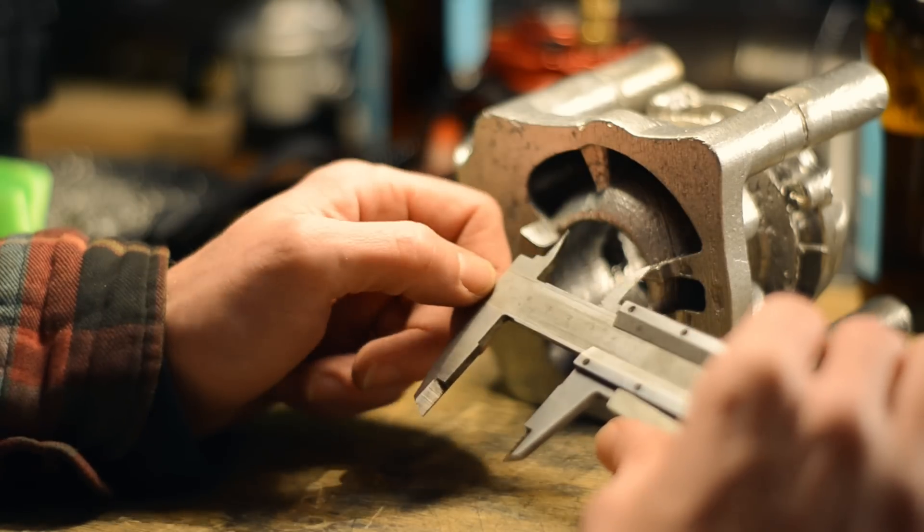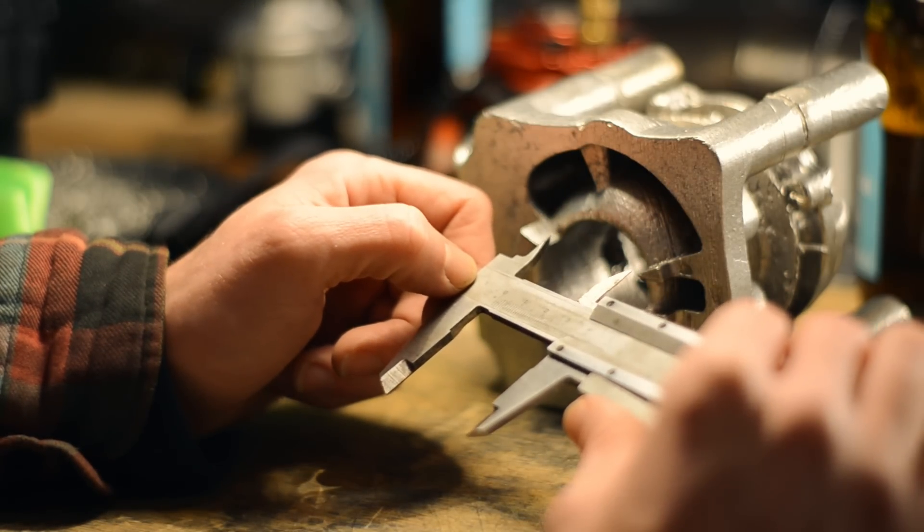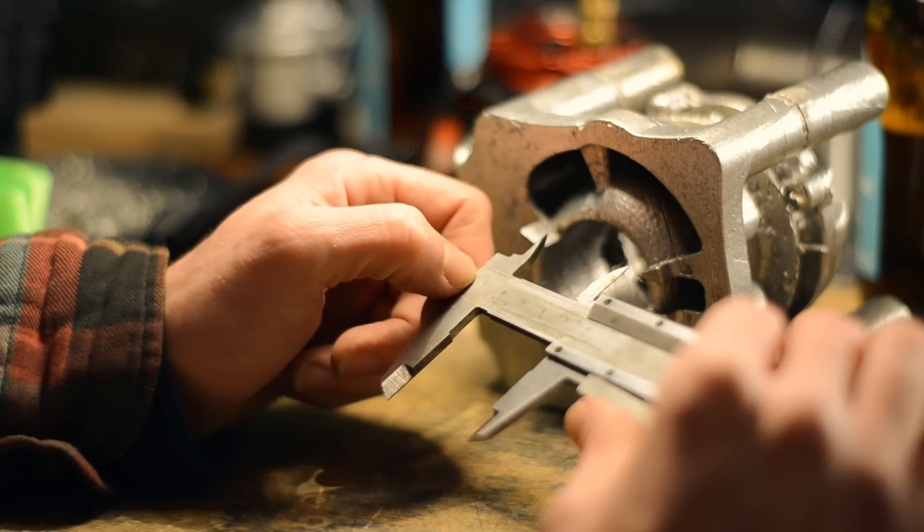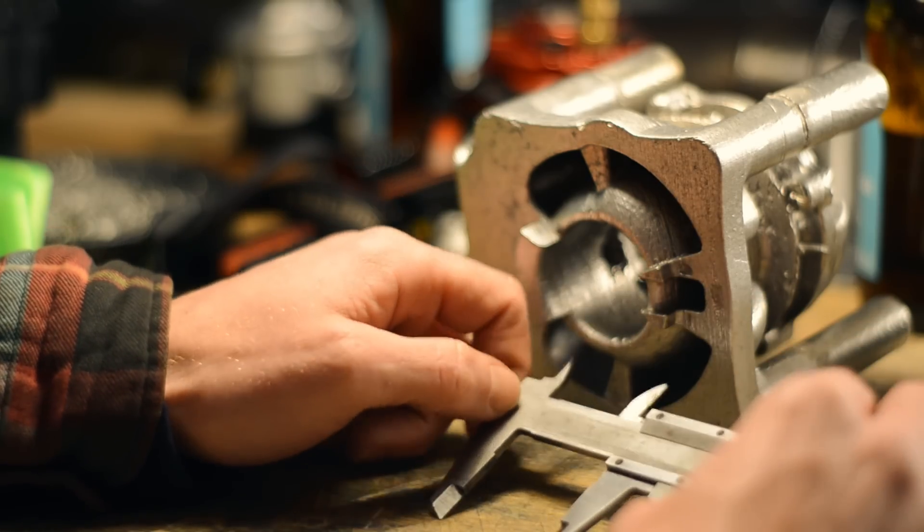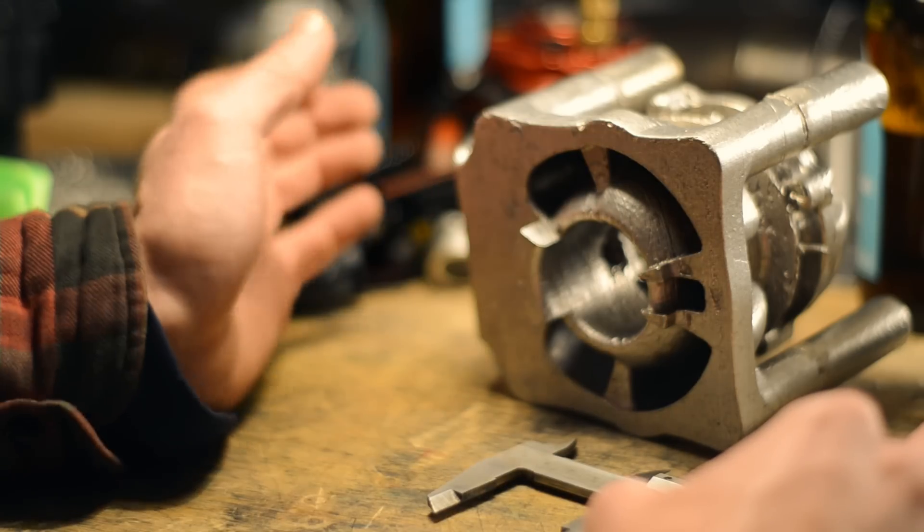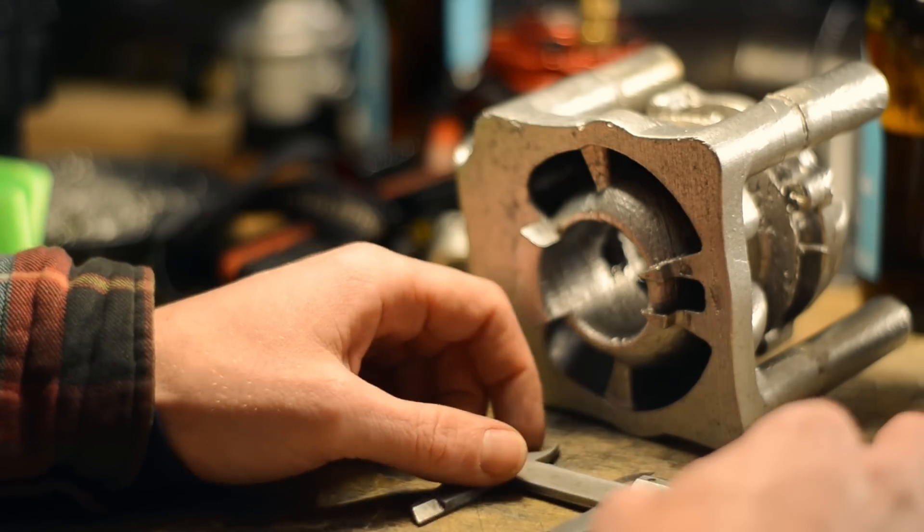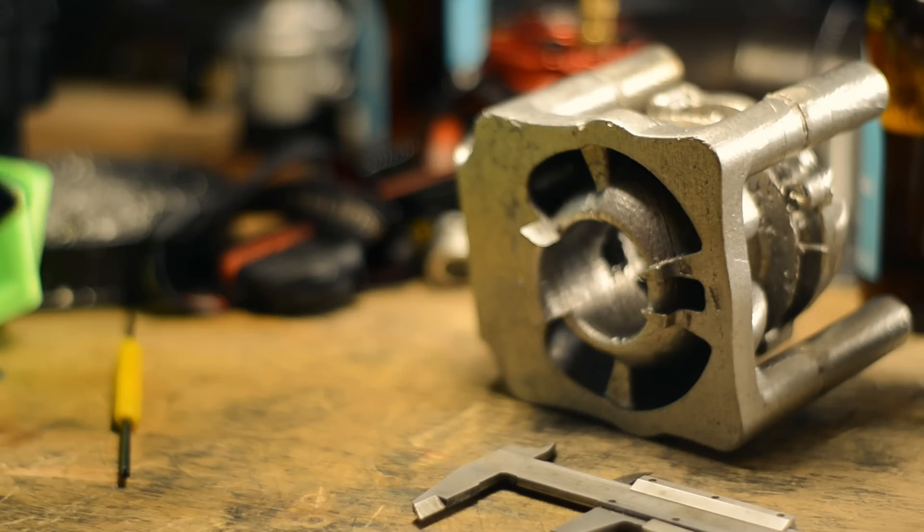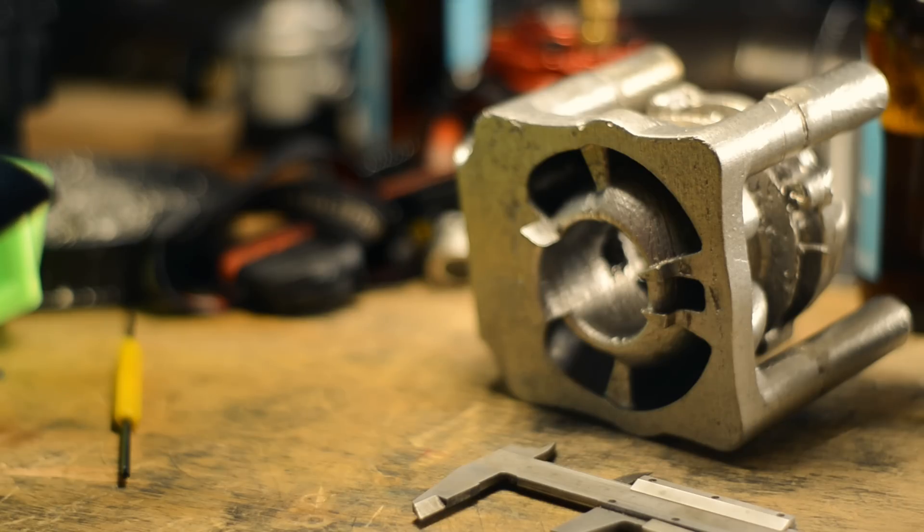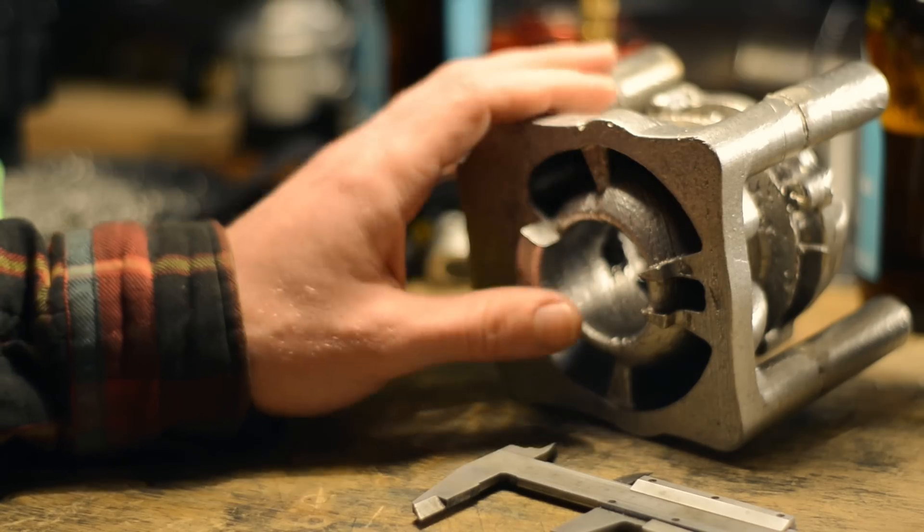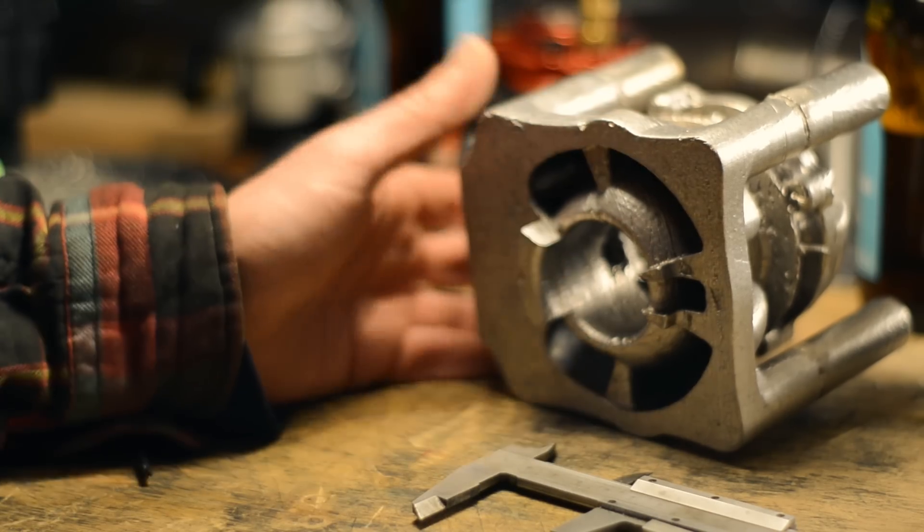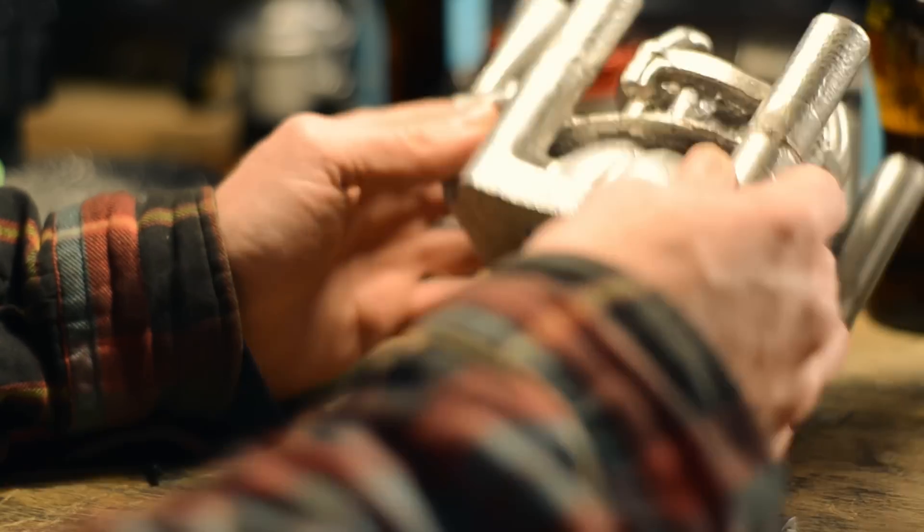The bore in the model was 40 millimeters, and here it's about 39.3 millimeters. So that's about maybe between one and two percent shrinkage. I'll have to check it on my calculator. 40 divided by 39.3, yeah, 1.017, so 1.7%. So I'll scale the model to 102% before I print the next one.